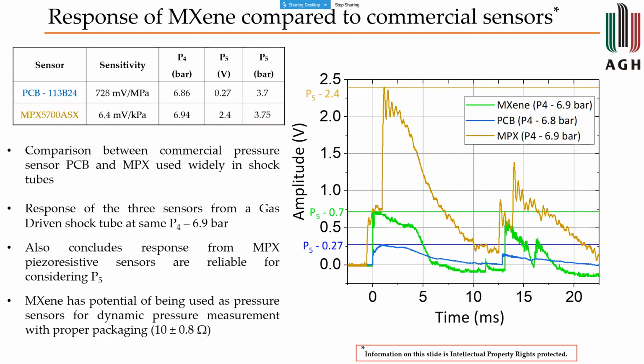We didn't want these samples to be put into a market phase where we could have them commercialized, because we would want them to go through a long repeatability cycle. So we've been testing them for the last 1 year with our collaborators, and for the last 1 year, the response of the material seems to be quite good. And we've prepared a lot more samples in the long duration, which could be repeated and tested again and again.